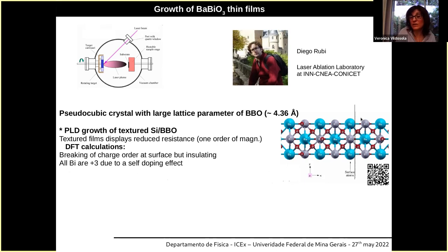We understood why, because in this orientation the system is heavily doped: there are apical oxygens that are absent, and the charge left behind by these apical oxygens that are not there anymore induces that there are more bismuth 3 plus in the system. So they characterized the film, and we studied them by DFT, and we could describe perfectly what the properties of this material were. But no metallic surface states were observed.